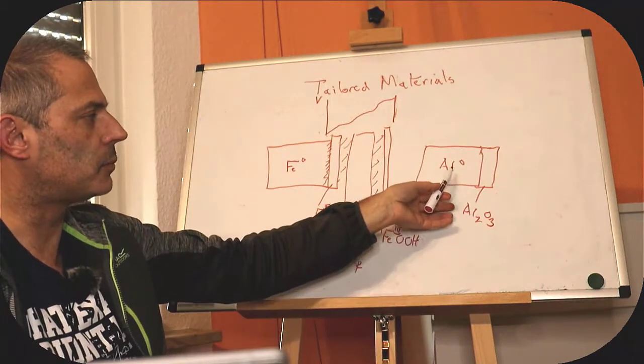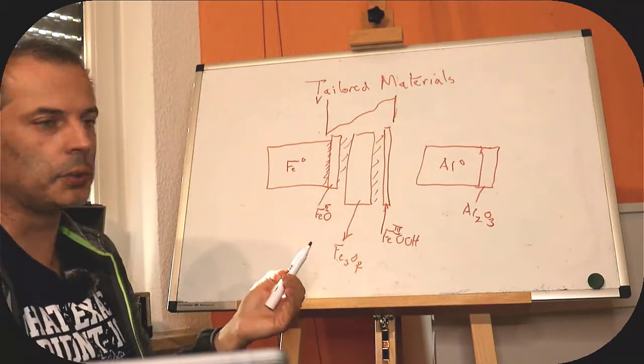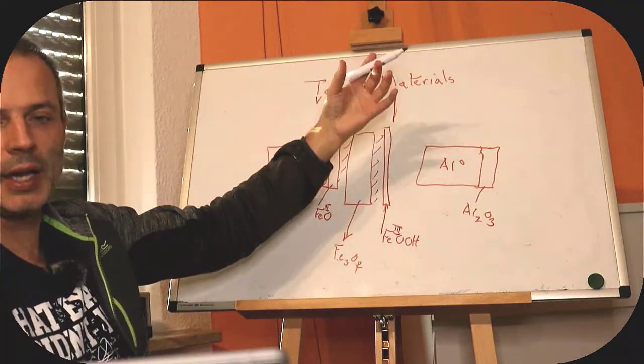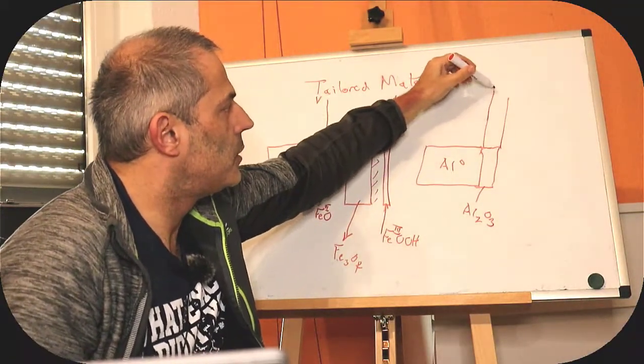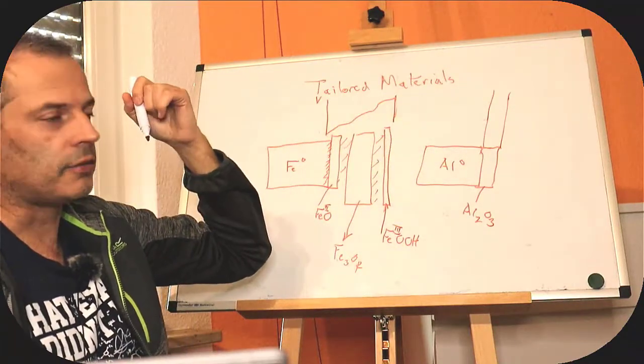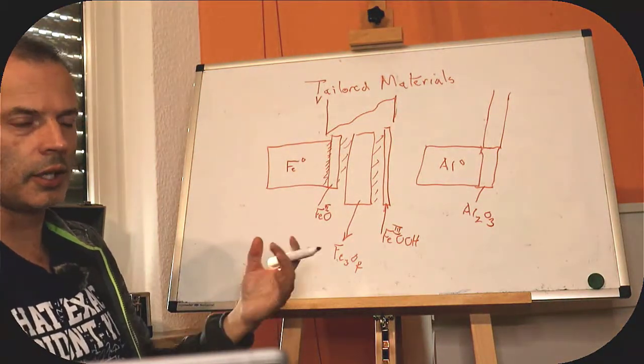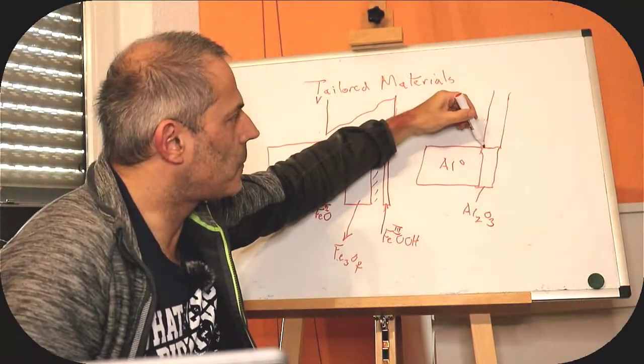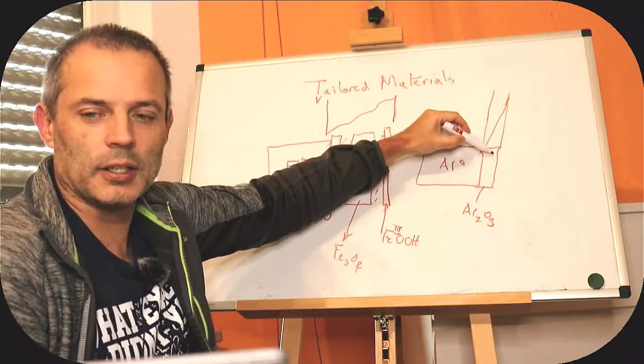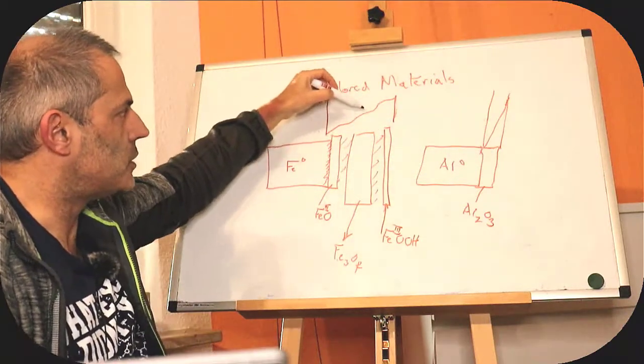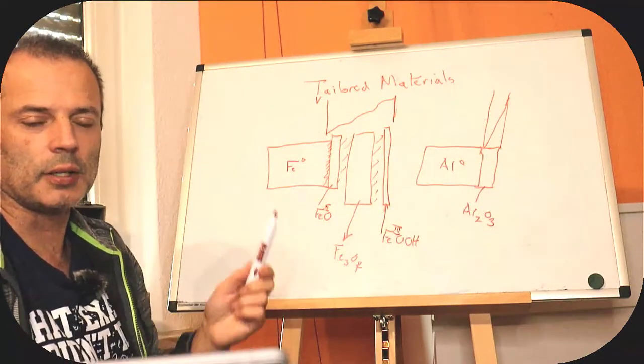But it could have some aluminum zero in the aluminum oxide. However, aluminum oxide is not very good at doing that. So aluminum oxide behaves like a good insulator. So now we've got our similar diagram. But in our similar diagram, we have a higher voltage difference because the aluminum is more electropositive, more reactive. And our air is the same point. The aluminum comes in lower. And there's nothing so exciting happening here.